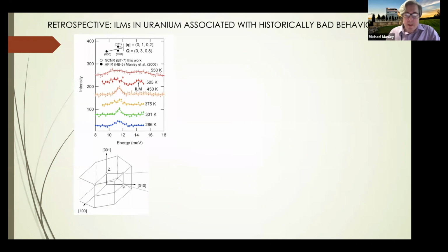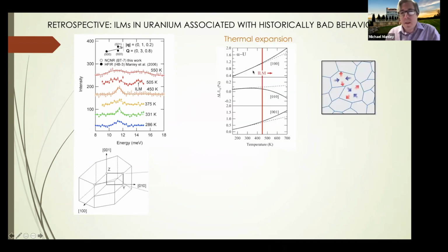If you look at it, as I mentioned, it tends to contract the lattice in the direction that it's polarized in. This localized mode in uranium appears around 450 K or 200 C. And if you look at the thermal expansion in uranium at that temperature, it undergoes a big change. The thermal expansion along the B axis in the crystal, 0, 1, 0, goes from positive to negative, and the other two directions go more positive, which is what you'd expect if you introduce ILMs.